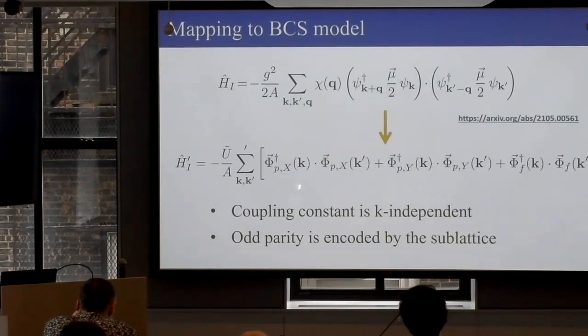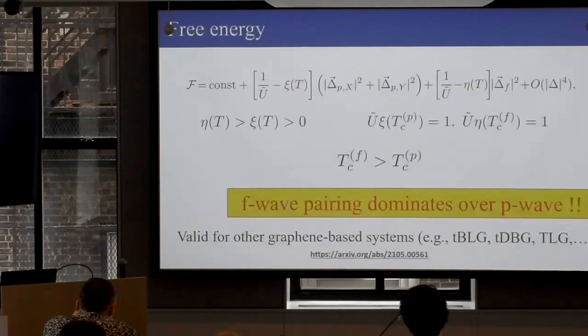Then we mapped into a BCS model. Here the coupling is K-independent, basically a Hubbard U-type coupling. And what we found here, the TC really is not that relevant because it's a phenomenological model. But what we found, this is the important thing: F wave pairing dominates over P wave. That is true here also for phonons, and here is for spin fluctuation. So this was our bottom line.